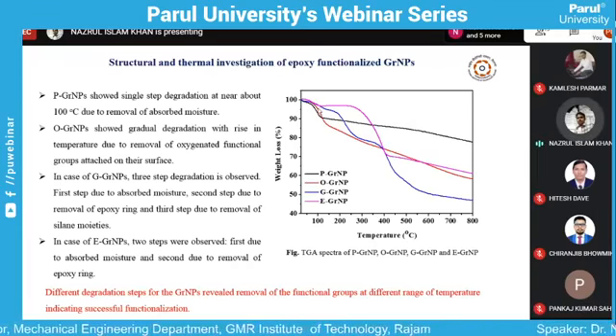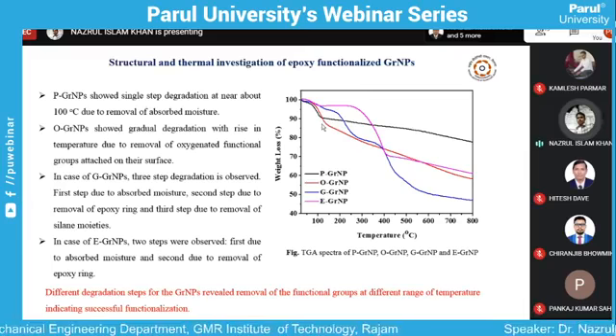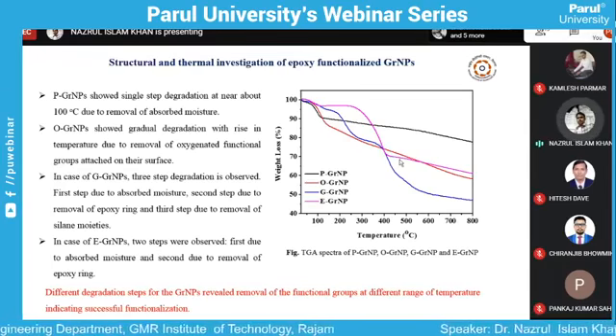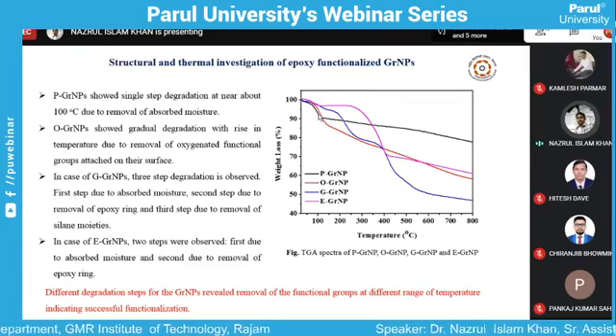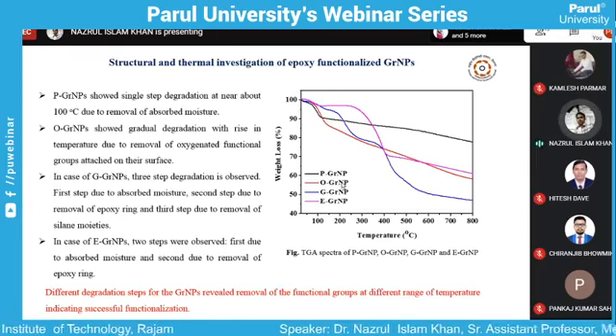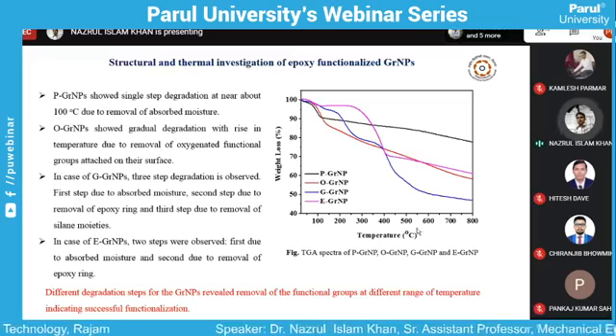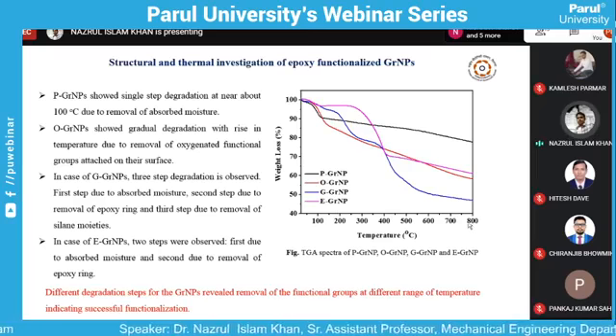But once we do the oxidation, you can see there is degradation that first started near 100 degrees, but continued throughout the process. Although the first degradation was due to removal of absorbed moisture, due to oxidation there are oxygenated functional groups attached on the surface, which continuously evaporate. Due to that, the red line shows continuous weight loss as temperature increases.